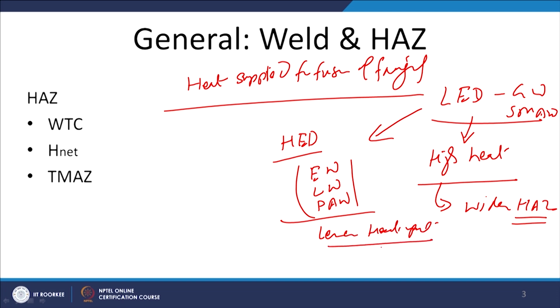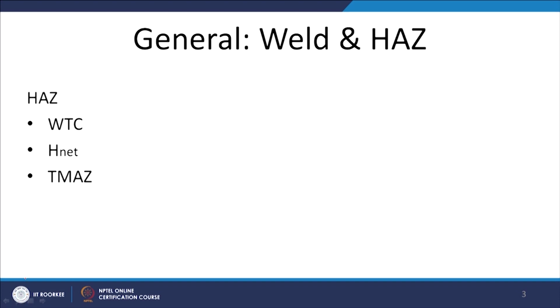So, the heat affected zone (HAZ) width in that case is reduced, and that in turn will help in addressing the issues to some extent which are associated with the heat affected zone. So, heat affected zone issues cannot be eliminated, but certainly they can be reduced to a great extent. The HAZ characteristics to a great extent depend upon the kind of weld thermal cycle being experienced by the base metal in the heat affected zone.